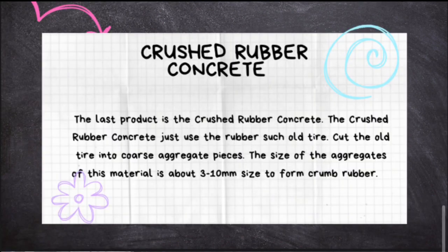And our final concrete is crushed rubber concrete. The last product is the crushed rubber concrete. The crushed rubber concrete just uses rubber such as old tires. Cut the old tire into coarse aggregate pieces. The size of the aggregate of this material is about 3 to 10 mm to form crumb rubber.